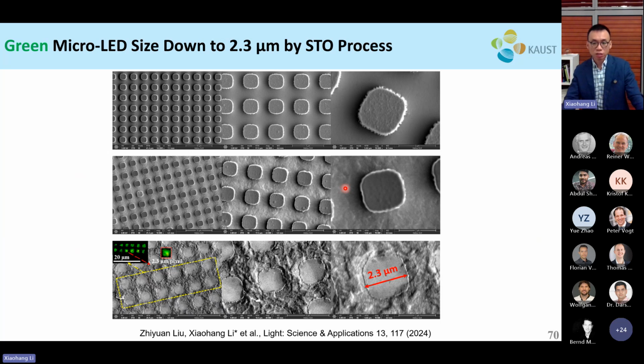What is the limit of this technology in terms of pixel size? We have also worked on it, it's preliminary data. We have pushed the micro LED size to about 2.3 micrometer. Okay, so vertically we anneal and oxidize to about 400 nanometers below the surface. Because we want to oxidize the entire p-GaN plus quantum well plus a little bit of the n-type region, but we can change the epi structure so that we can reduce the amount of vertical oxidation. Because when the vertical oxidation happens, you have the lateral oxidation too. That will limit our micro LED size. But so far we have pushed the size to about 2.3 micrometer, and we hope that we can push this further down to 1 micrometer or so in the future.